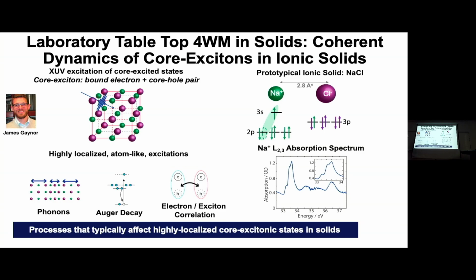And this type of feature is called a core excitonic state, or a core exciton. It's been studied a lot to understand the mechanisms of the decay. They're very short-lived states. They could decay by a phonon mechanism, or by an Auger process, where one electron falls down and another is released, or by electron-exciton correlations or exciton-exciton correlations. There could be a lot of different mechanisms in a solid that you don't have available in a gas.